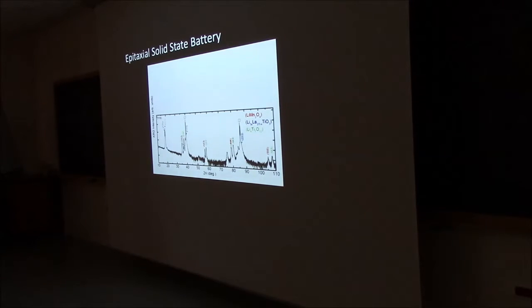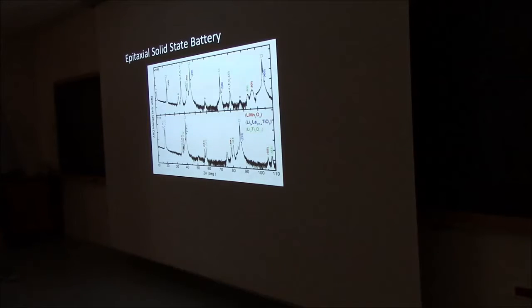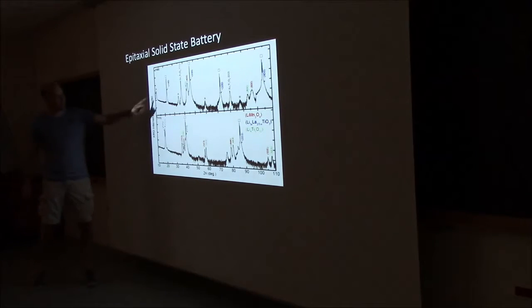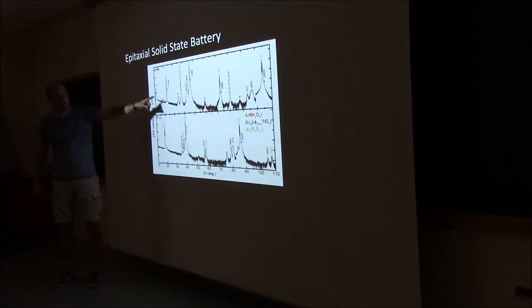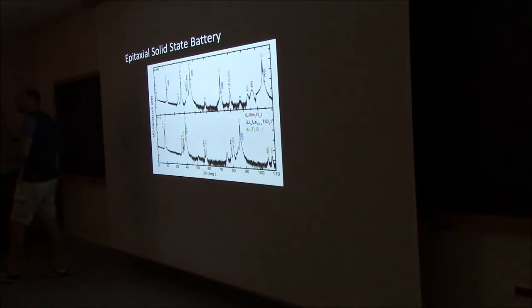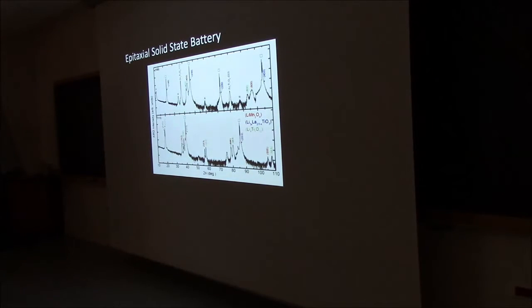If we do it on the 1-0-0 orientation with these pyramids, that's a different story. Then you can see some of the phases, but you can also see anatase, you can see rutile, all kinds of other things are happening as well. So that's not so stable at all. So in this kind of stack, we're focusing on this bottom one.